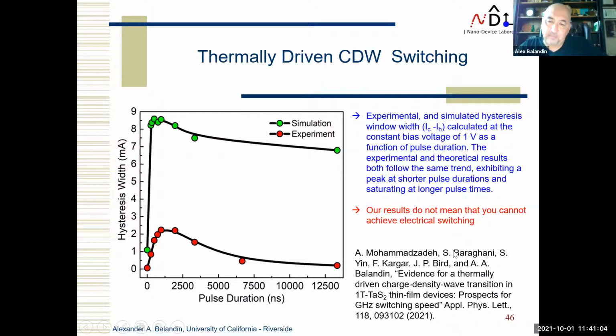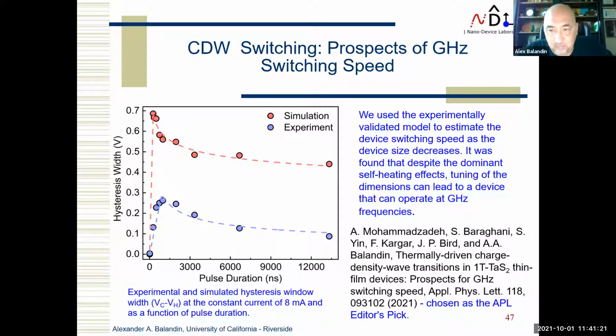But now that we have this experimentally validated model, we decided to say, okay, if my device were smaller, comparable with our silicon CMOS, then it would take less time to heat up the sample, right? So we took this validated model and checked what would happen if you optimize the device size. I see that you can hear me, right? Okay. If you optimize device size, we showed that you can go to very short pulses, which would correspond to gigahertz switching speed. So in principle, even if these devices are driven by heating, they can be fast.